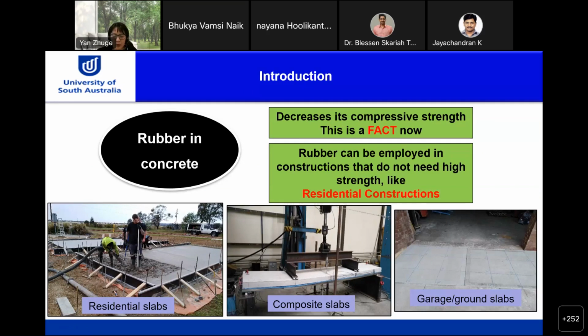Therefore, crumb rubber concrete is probably most suitable for structures that do not need very high strength, like residential construction. Very interestingly, our research also found that the flexural strength of concrete was not really affected by the inclusion of rubber. Although there's a sharp drop of compressive strength, the flexural strength was not significantly reduced at all in the 3-point bending tests of a lot of concrete slabs. That's a very interesting finding.